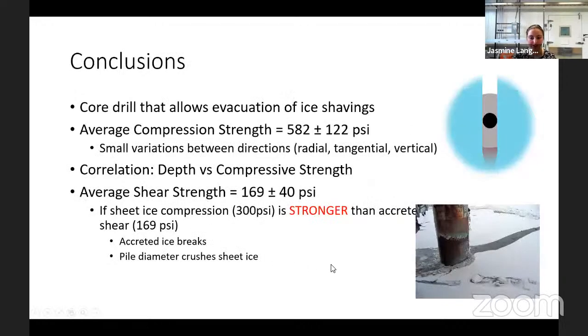All right, so some conclusions from the ice core drilling. We determined that the most important thing was to have a place for the ice shavings to evacuate. And as I mentioned before, the average max compression strength is 582 plus or minus 122 psi. There are some small variations between the radial, tangential, and vertical directions. And there's one significant correlation, which is depth versus compressive strength. And the average shear stress is 169 plus or minus 40 psi.